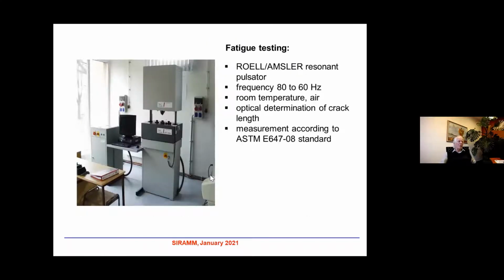We have performed tests on Roell Amsler resonant testing systems. The frequency of loading was between 60 and 80 Hertz. Experiments were done at room temperature in air. The cracks were, in our case, determined by optical measurements by microscope or CCD cameras. And the measurement was done according to the ASTM standard, which prescribes the conditions of testing.